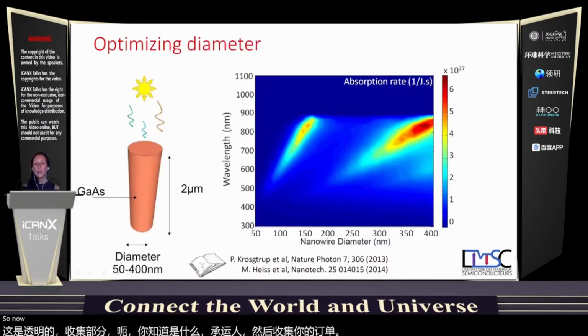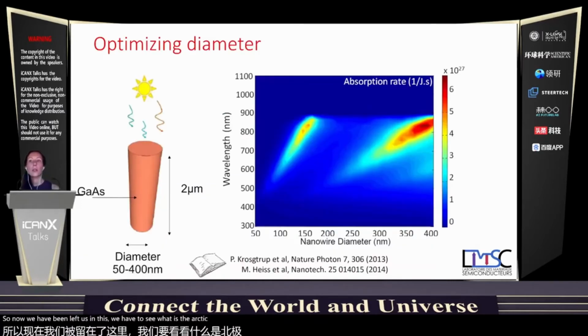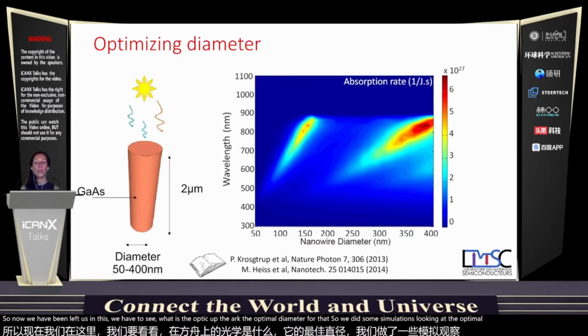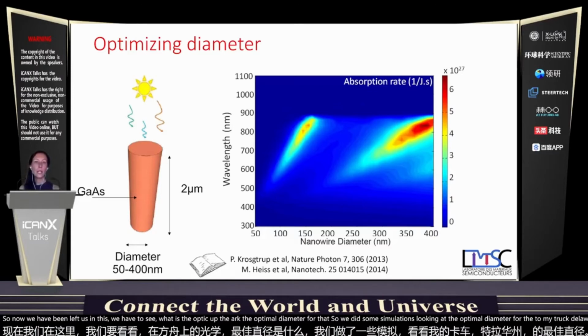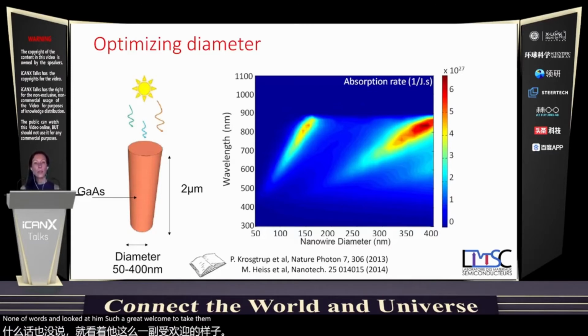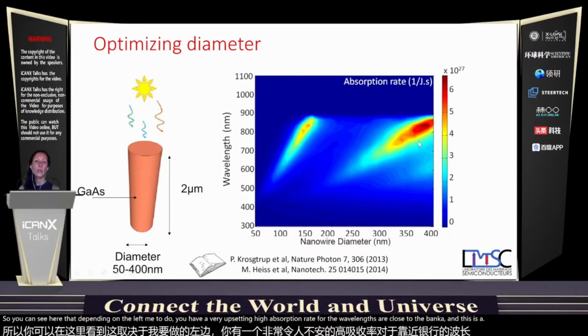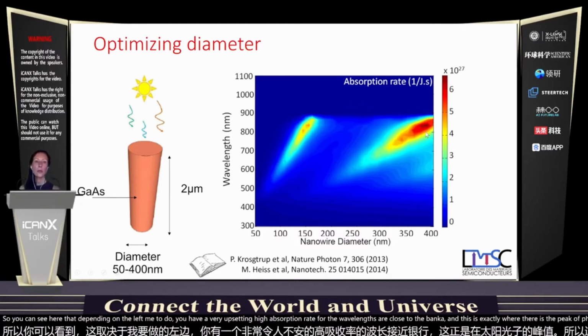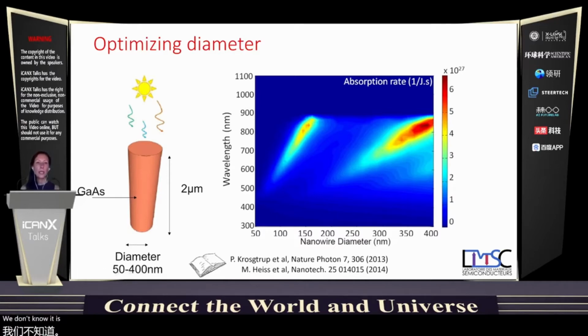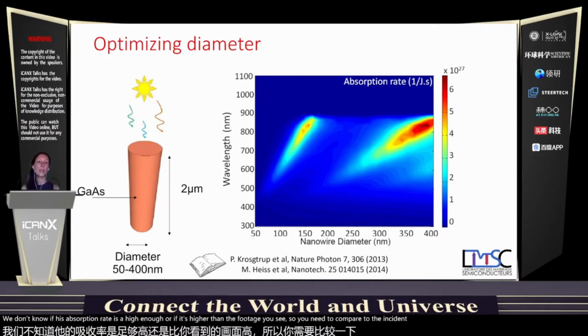So now after seeing this, we have to see what is the optimal diameter for that. We did some simulations looking at the optimal diameter for the 2-micron gallium arsenide nanowires, and we looked at the absorption rate when you illuminate them with one sun. You see here that depending on the diameter, you have very high absorption rates for wavelengths that are close to the band gap. And this is exactly where there is the peak of photons in the sun. So it's quite good that we have a high absorption rate here. Still, we don't know if this absorption rate is high enough, so you need to compare to the incident rate of photons.